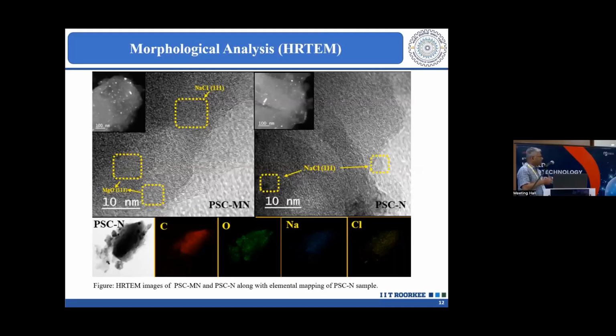the sodium. And this shows the TEM morphology, this material has a carbon structure, which is amorphous. Then if we look very critically, we can see the magnesium oxide crystalline phase is also present, and the sodium chloride is also present. And since this one has no magnesium oxide, it only shows the sodium chloride. So it is a mixture of amorphous and crystalline, and only part of it is crystalline.